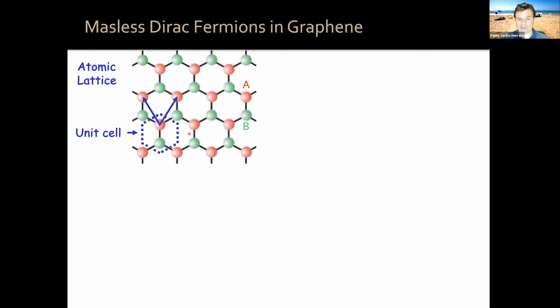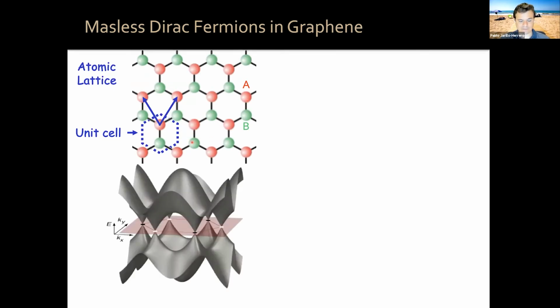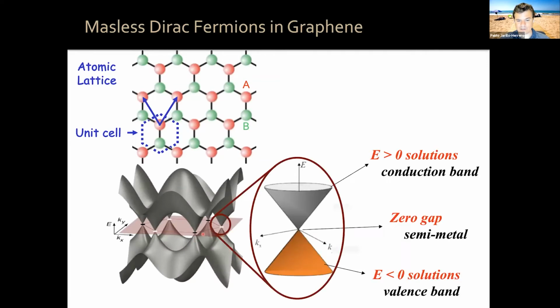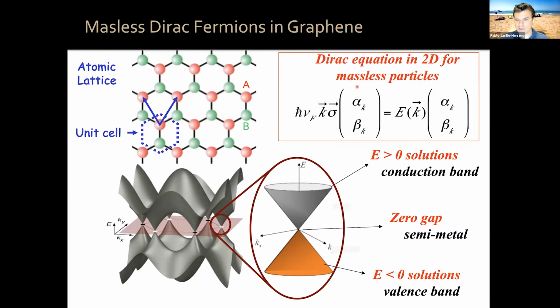You can calculate the electronic structure of graphene in a simple tight binding model, and you get this very unusual electronic structure where near the Fermi energy, you have these double cones. They're called the Dirac cones, where the energy versus momentum relation in two dimensions is linear. This can be formalized in a Hamiltonian equation. This is nothing else but the Dirac equation in two dimensions for massless particles.